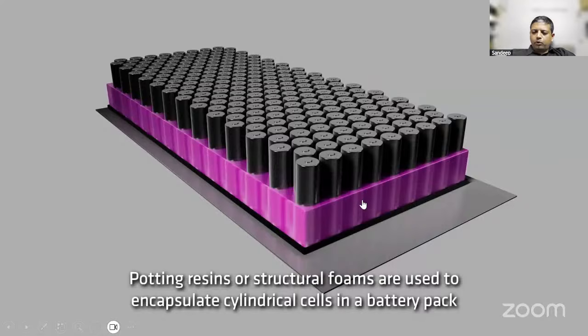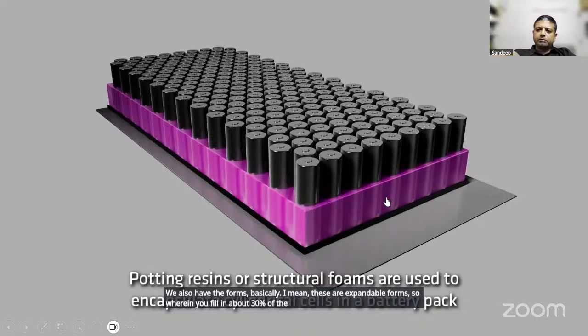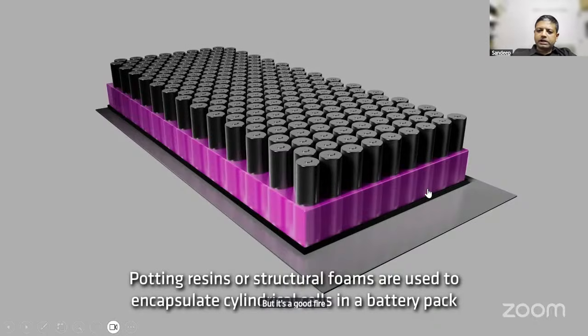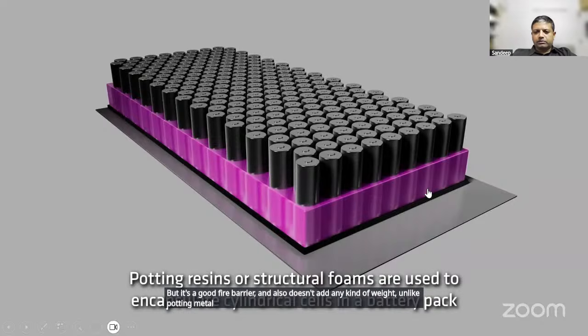We also have the foams basically. These are expandable foams, wherein you fill in about 30% of the pack with the liquid material and then it expands and fills up the entire pack with the foam. The only problem with the foam is that it doesn't really give you any kind of thermal conductivity, but it's a good fire barrier and also doesn't add any kind of weight, unlike a potting material or a thermal gap filler, which is a pretty high density material.